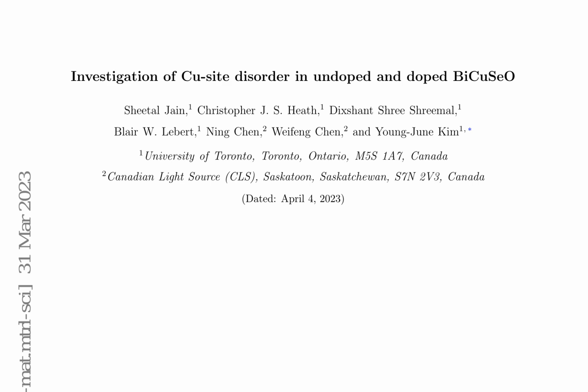Rietveld refinement of the temperature-dependent XRD data yields the temperature dependence of the lattice constants of the tetragonal unit cell and isotropic mean square displacements of each atom for undoped BiCuSeO, as presented in Figure 3. The temperature dependence of lattice constant A reveals uniform thermal expansion from base temperature, 93 K, to room temperature, 298 K, followed by a subtle increase in the rate of expansion up to 700 K, and then a decrease in the rate up to 1023 K. The relative thermal expansion behavior is nearly identical for lattice constant C, with error bars smaller than the symbol sizes.